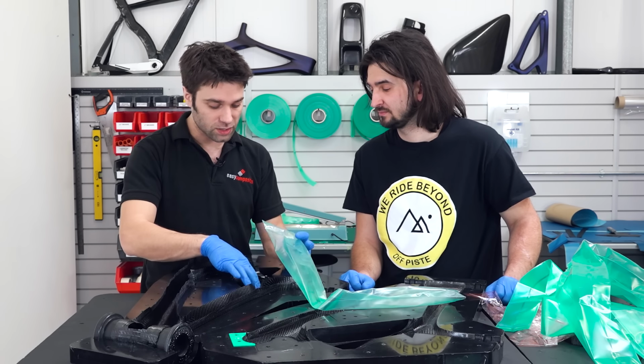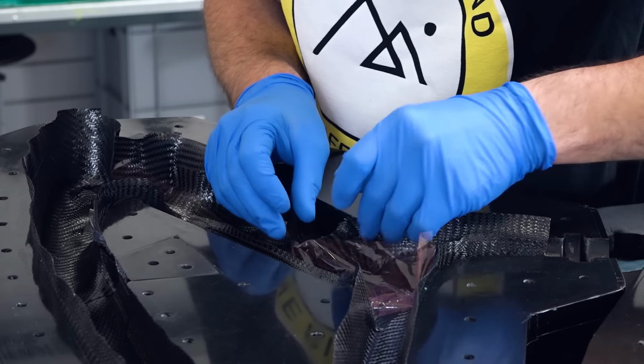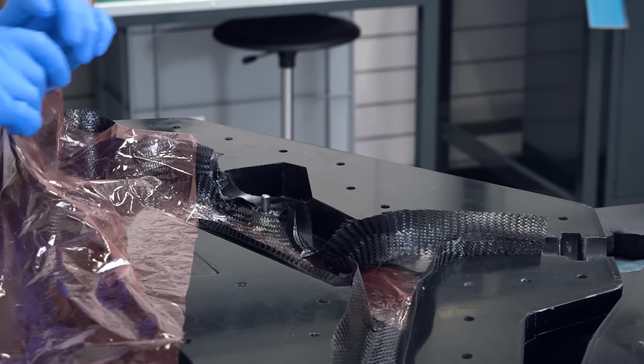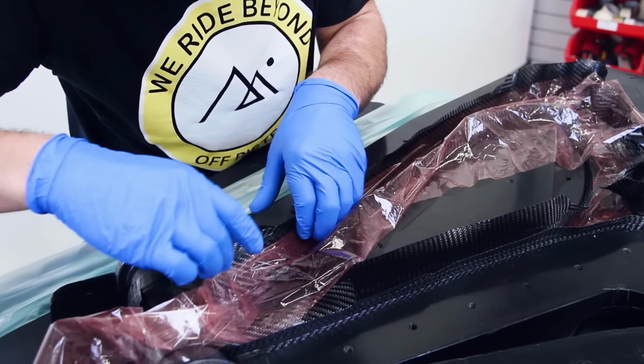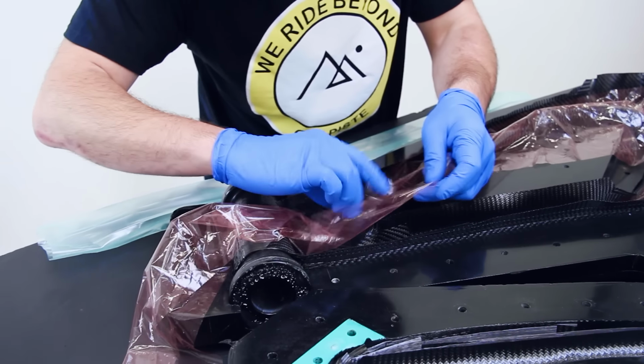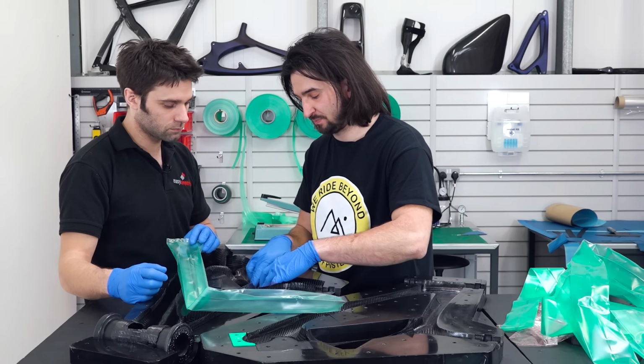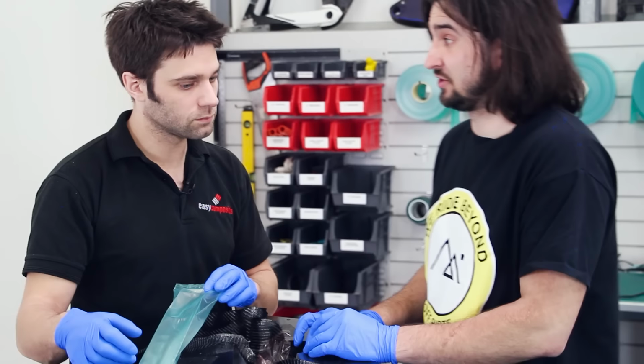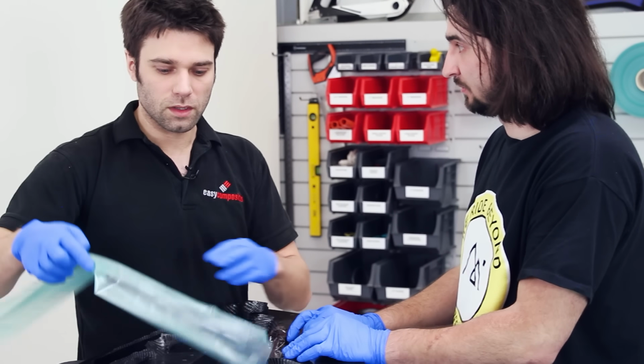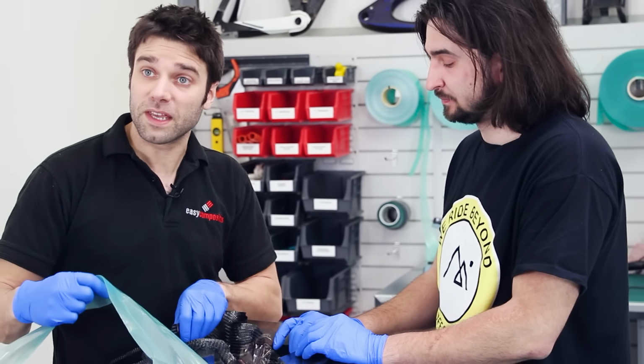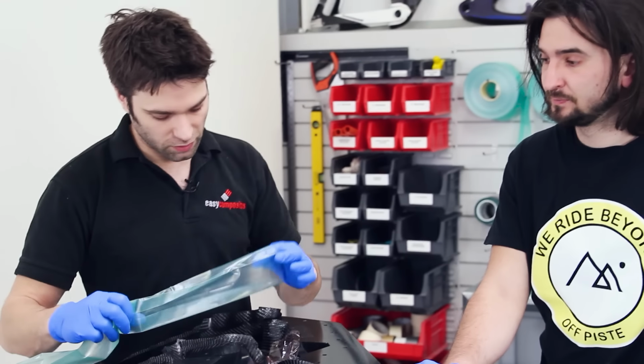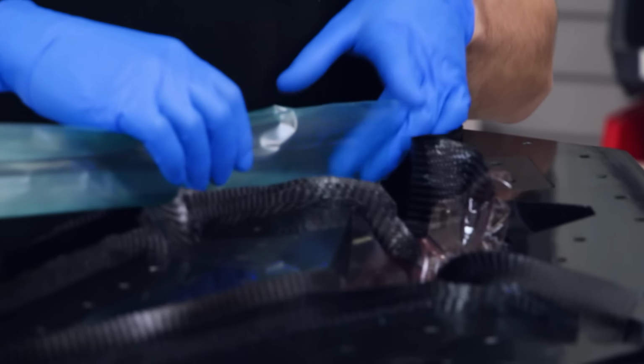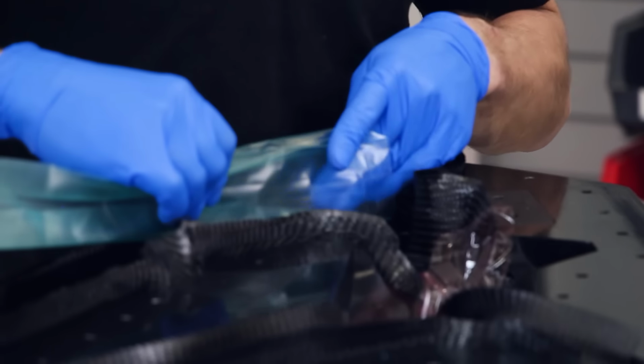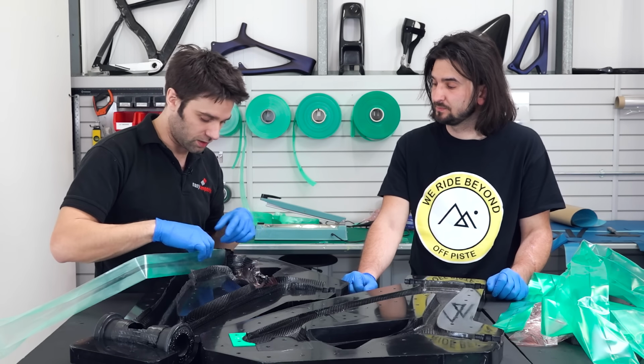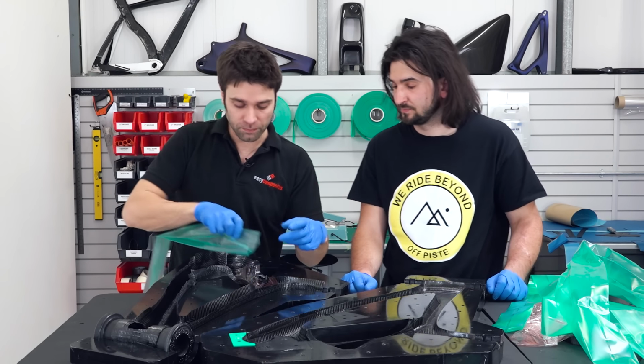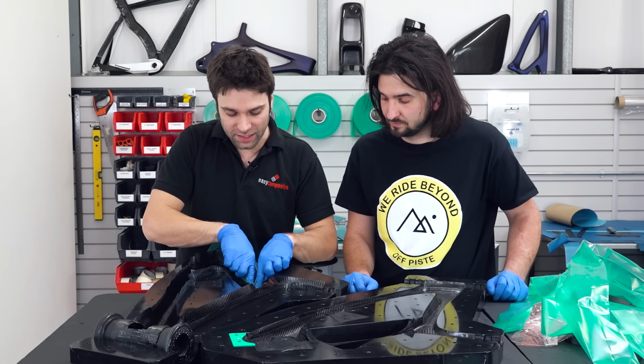But before that, I understand you're going to put some release film down, and that's there to stop the bag from gripping onto the surface. Yeah, we did put some release film down just on the half where the laps are. It basically will allow the bag to slide and position itself into the mould when we apply the vacuum. With the pre-preg being quite tacky on the surface, you've got the vacuum bag. If you imagine having a bit of pressure against that, it's very difficult for it to slide and move out into the frame. So if we use some release film, that then lets the bag sit in and slide around.